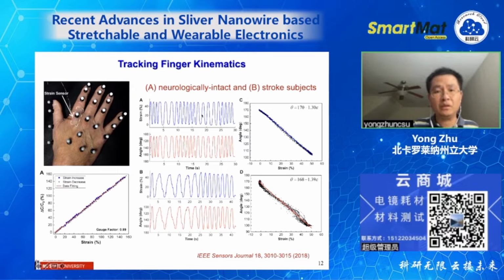We tested on two groups of people. The top, A, is from a healthy subject, just bending the finger multiple times. You can see the strain measurement and also this optical measurement are almost perfectly matching. So it speaks to the accuracy and the response speed of our strain sensor. Panel B is about a stroke subject. For stroke subjects, the motion is a little involuntary, with more complicated patterns, some jerky motions and so on. But again, look at these fine details. Our strain sensor can still capture all of them, again showing excellent correlation. So the sensor works very, very well.